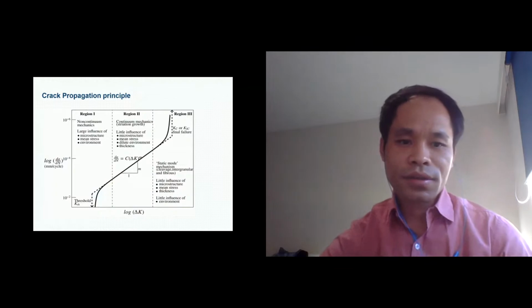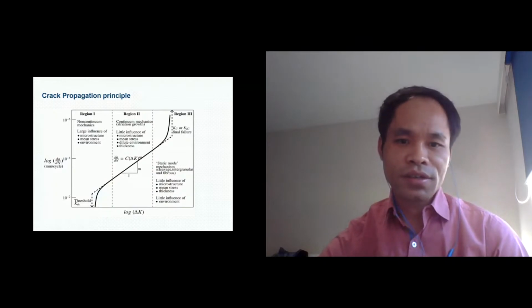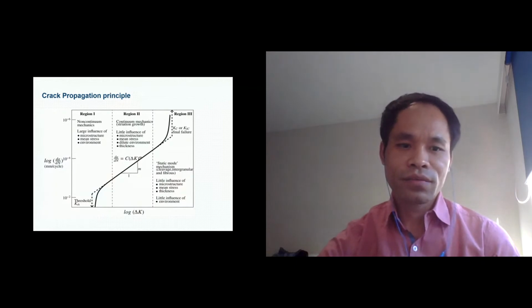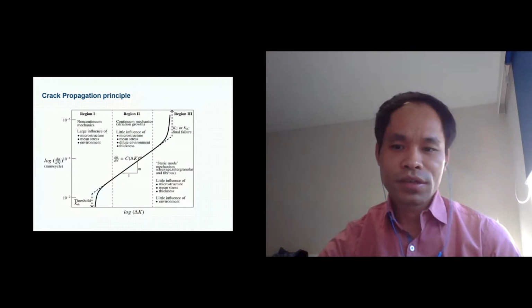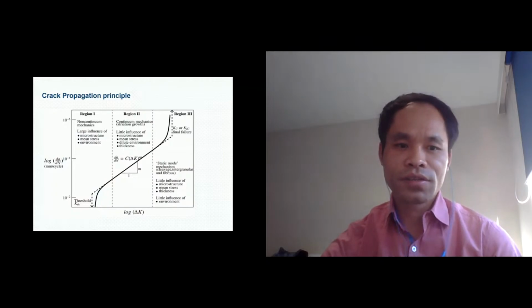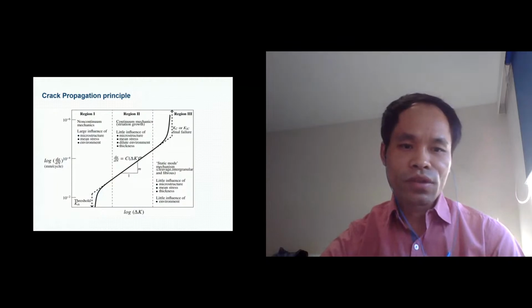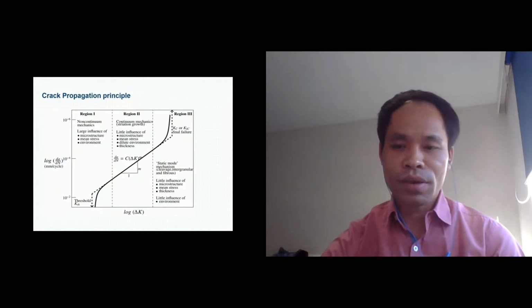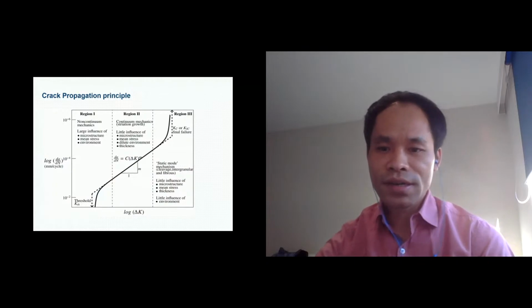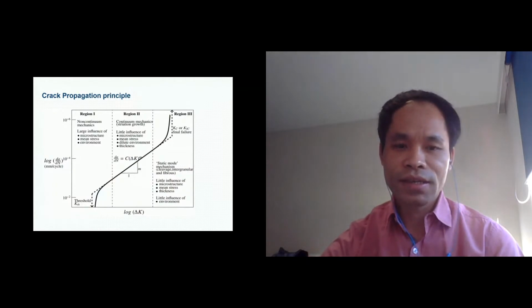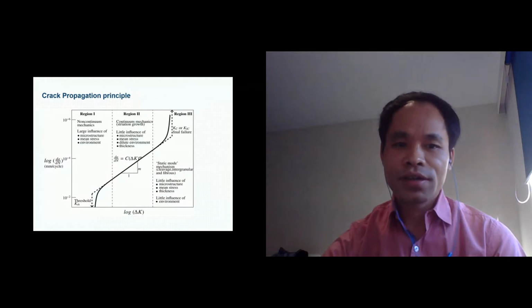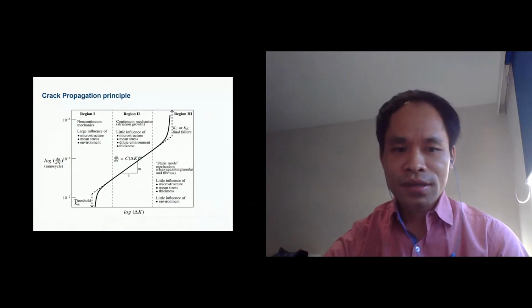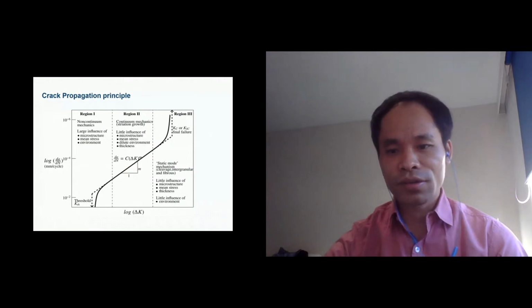According to research, in the crack growth models there are three regions which we can identify. The first one is region 1, which we call the crack initiation region. In this region, growth is largely influenced by microstructures, mean stress, and environmental conditions. But region 2 is the region where there is a crack with steady and linear crack growth. According to the research, region 2 is linear and steady, and it is little influenced by the microstructures, stresses, or the environment and thickness of the materials.